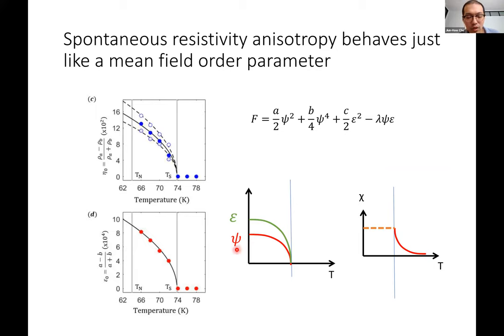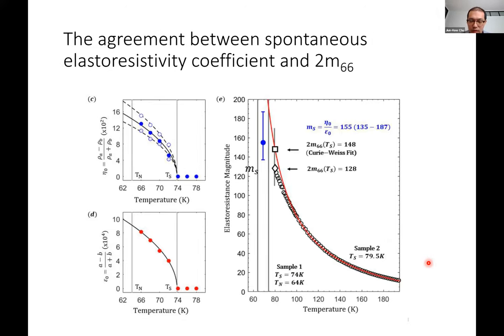So if the resistivity anisotropy is truly a good representation of the nematic order parameter, and this whole free energy framework works, then we expect that the ratio of these two quantities will be the same as the elastoresistivity coefficient at the transition temperature. So we measured the elastoresistivity coefficient of a crystal from the same batch, and the answer is that they do match. The ratio of this quantity is around 150, and the elastoresistivity also reaches about the same value at the transition temperature. That really means you can consider the resistivity anisotropy just like a nematic order parameter, and that the mean field free energy works.